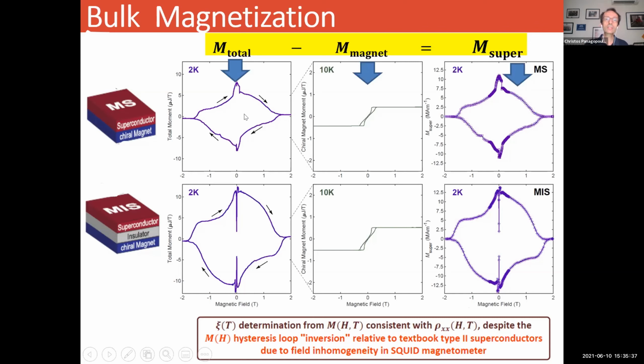On the top row, you will see data for the MS system, and the bottom row is for the MIS system. On the left-hand side, the left column, is the total magnetization. The middle column is just the magnet on its own, and the right column is the difference, that is the superconducting component. Now note, and I would like to mention this, that the temperature dependence of the superconducting coherence length from the magnetization data is consistent with the transport data, despite the fact that the hysteresis loop is inverted relative to textbook type 2 superconductors. And this inversion is purely because of the inhomogeneity in the magnetometer.